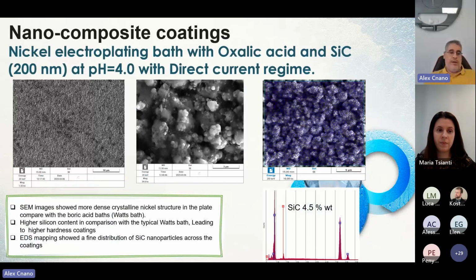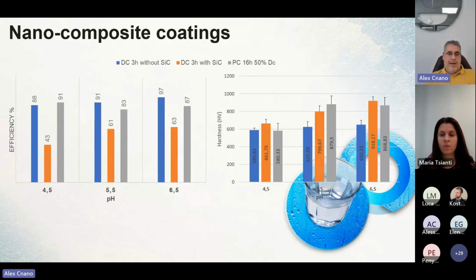As Luca said, a very big effort is also made on nanocomposite coatings. Here we have a composite coating with a new type of bath other than the Watts type. We have used, instead of boric acid, oxalic acid, and nanoparticles of silicon carbide with a size of 200 nanometers, using a standard pH of 4. With direct current, we can see that we can have a good distribution of the silicon carbide. We have reached 4.5 weight percent. Of course, by utilizing more advanced methods like pulse current plating, this can increase. And as you can see, we make comparisons of the efficiency and hardness of different types of coatings for different types of applications.